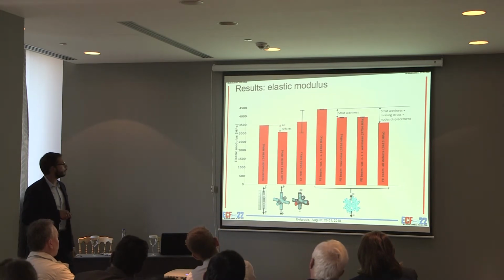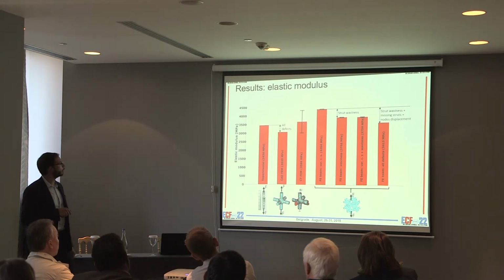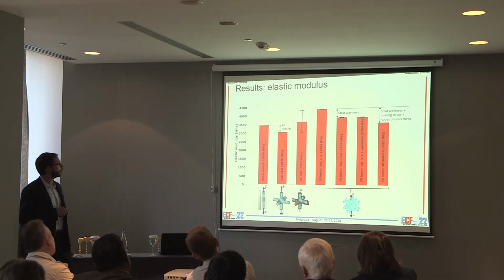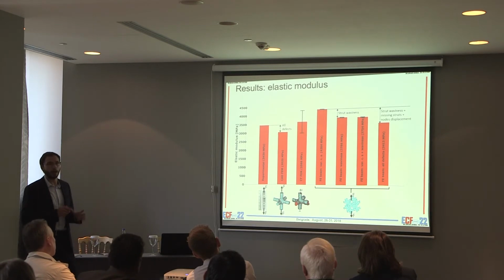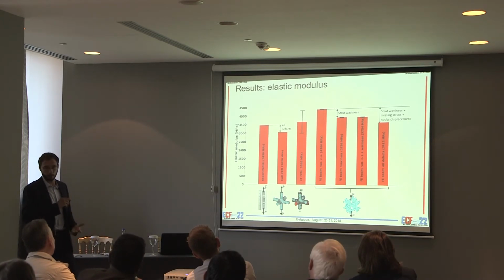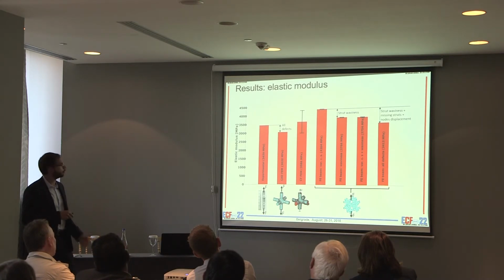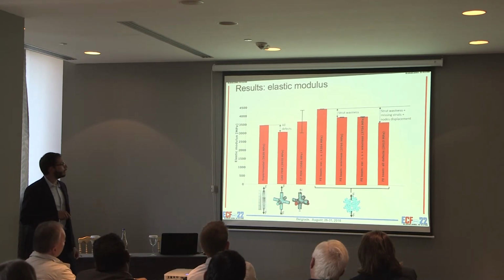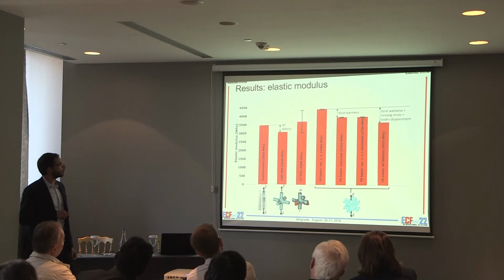In fact, if we take the value measured from the solid model taken from the tomography, we see that the value is closer to the experimental value, although there is a big variability due to the fact that I used only a single junction and not the entire specimen. It's a mean of 8 different junctions, obviously due to the variability of the process. It is significantly scattered.